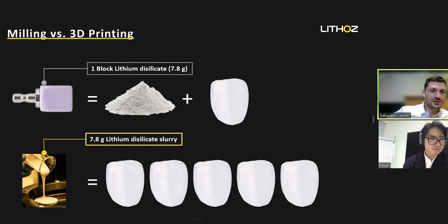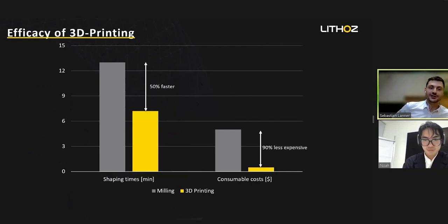And what you see here again is the shaping time comparison on the left side in minutes, as we have in printing the parallel production with up to 50 restorations. And when you go milling lithium disilicate, you have just one after one. And so this leads us to the point that we can get much, much faster in our printing process.